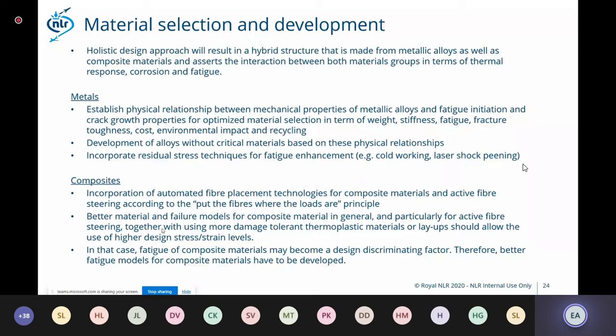So for metals, we still see that there is a lack of relationships between the mechanical properties and fatigue crack growth. Because, for example, when you look at fatigue crack growth of annealed materials, if you look at aluminum annealed, then the crack growth rate is exactly the same as for a T7 heat treatment. Where you see the difference is for crack initiations.